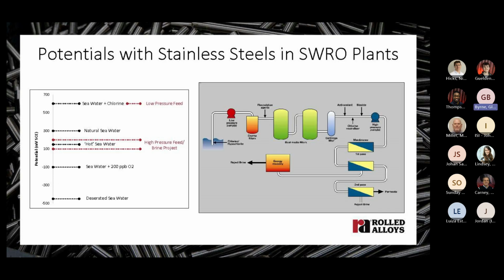The figure on the left shows the potential of stainless steels in seawater, how it varies with water treatment. This is important because the higher the potential, the higher the risk of pitting and crevice corrosion. The figure on the right is a schematic representation of a seawater reverse osmosis plant. For a stainless steel in natural seawater, the potential is about 350 millivolts versus the standard calomel electrode once the biofilm has formed. If the seawater is disinfected continuously with about half a ppm of residual chlorine to prevent fouling, the potential is typically plus 600 millivolts, as you can see here.